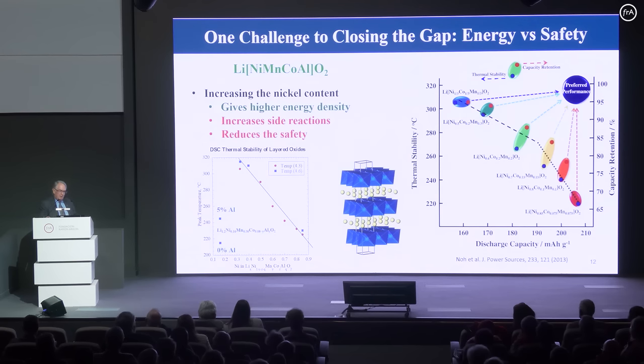So all these materials, if you take lithium out, and the same with pure lithium cobalt oxide, they're unstable, so they can evolve oxygen. Under the right circumstances, they will evolve oxygen, and this is what causes thermal runaway and fires in the end. So the more nickel you put in, the less stable they are. Our goal is to increase the stability of those materials so we can increase the energy density and cut the cobalt out, and I'll just show you two variations. It doesn't really matter what else you put in these materials. The stability is directly related to the nickel content.